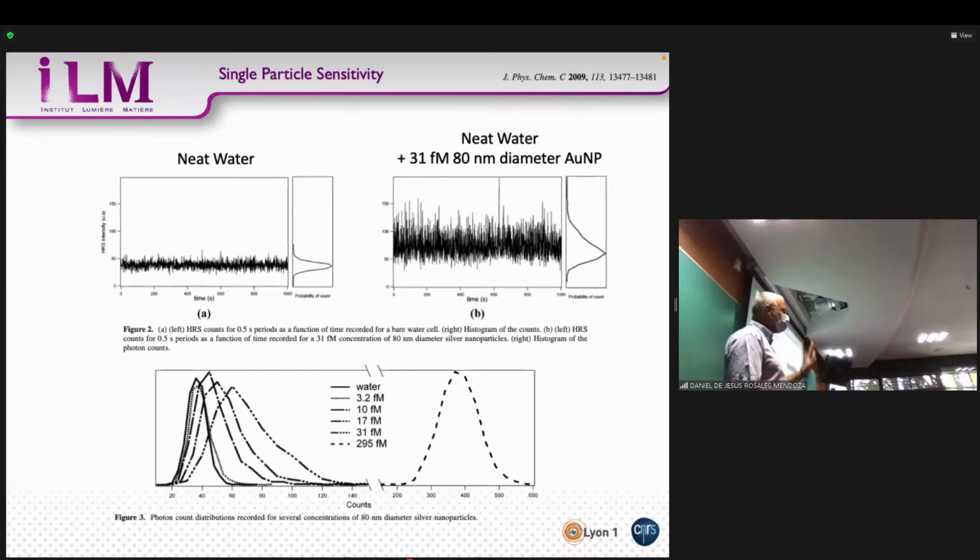The only difference would be with the surface plasmonic resonance. There are interesting features, actually, because you've seen the plots. One is 2 lobes, when it's purely dipolar. When there are 4 lobes, it's actually a quadrupole response. And the surface plasmonic resonances do not have the same wavelengths for dipole and quadrupole surface plasmon. Therefore, you can favor one compared to the other. So what I've hidden is the fact that you can slightly play with this coefficient by just tuning the wavelengths.